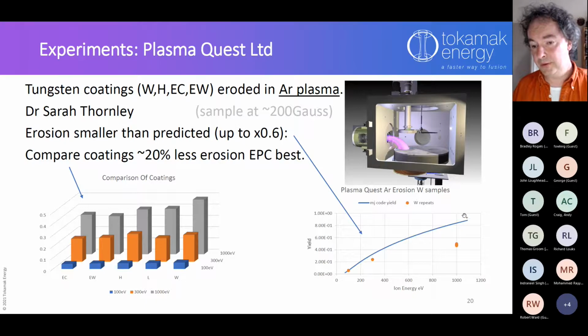Here's a blue line, which is from my code again, and the orange spots are the results from Plasma Quest using the argon plasma. So the code can be changed to work for any ions, argon ions, helium ions, hydrogen ions, whatever you like. Just a very simple change in the code, and we can produce these graphs. So again, it kind of follows the right trend. In this case, it is lower as opposed to the other tests that we did, which was higher.